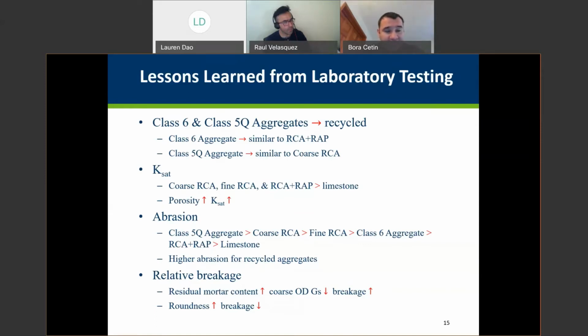And then we look at the relative breakage under compaction. As I mentioned before, especially coarser graded RCAs may have a high relative breakage, and that is directly related to the residual mortar content. If you have high residual mortar content on your RCA material, you tend to have high breakage potential, which, under compaction, will alter your original gradation and end up with a finer gradation curve, which may impact the stiffness and the permeability of the material a little bit. And the angularity of the material also impacts the breakage. If you have more rounded aggregates, of course, the breakage ratio will decrease significantly.